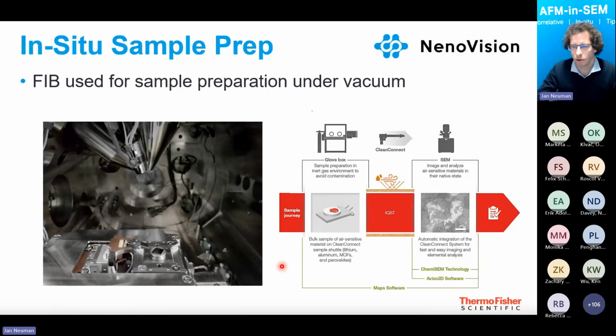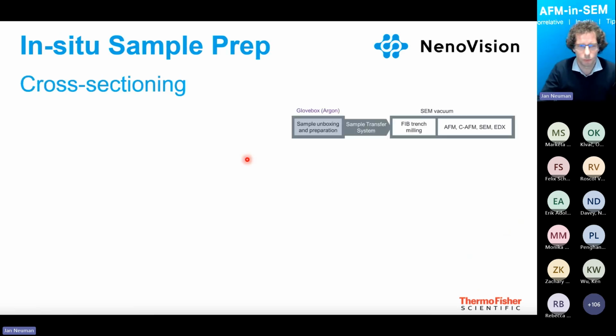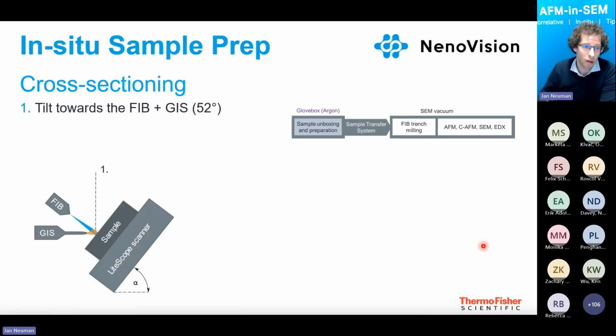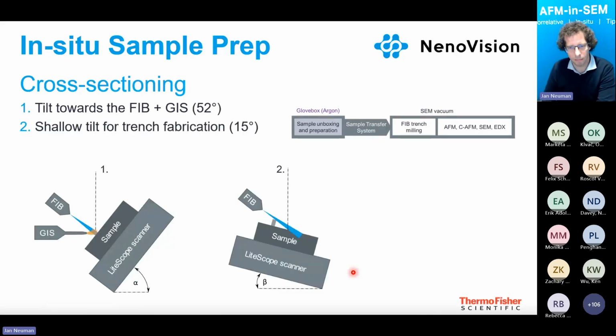Then the workflow is a bit different because we directly take the sample from the glove box and put it directly into the SEM, equipped, of course, with the focus ion beam, gas injection system and the AFM. If we want to prepare the cross-sectioning, we have developed the workflow as follows. First, you can tilt the whole AFM with the sample towards the focus ion beam, and using the gas injection system, you can build a so-called protective layer.